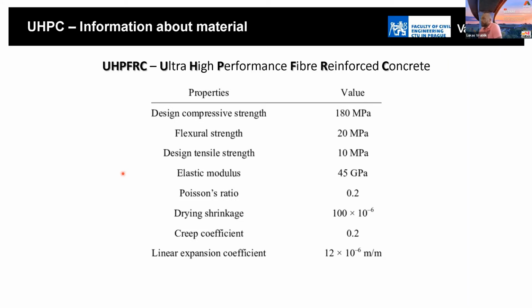As I said, very important is the tensile strength, especially flexural tensile strength. Compared to normal concrete, we have something like 10 times higher, because normally we obtain approximately 20 megapascal. Design tensile strength in pure tension is less than 10 megapascal, approximately 10 megapascal at maximum. Also, the elastic modulus is a little bit higher compared to normal concrete. Poisson's ratio is the same, and also the linear expansion coefficient due to temperature loading.